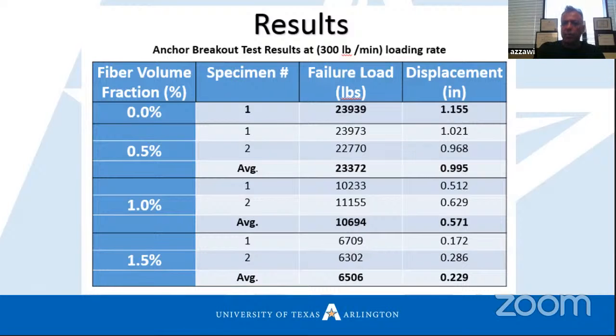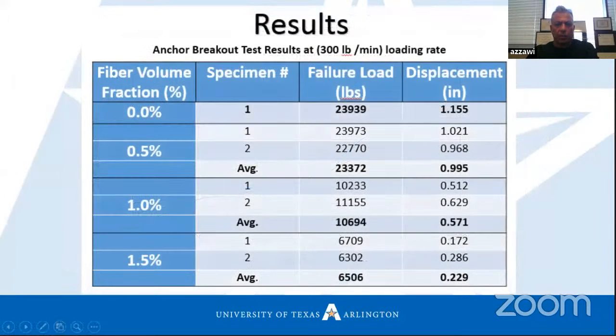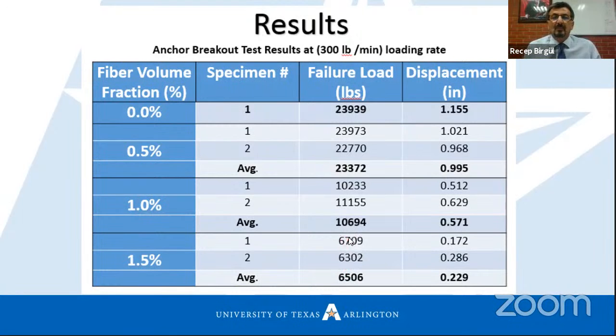So with synthetic fiber, I recommend going with 1% fiber dosage, not more than 1% fiber. I don't recommend going with more than 1% fiber with synthetic fiber. With the steel fiber, yes, we can go more than 1%, but with synthetic, increasing fiber more than 1% will really affect the workability and also the compressive strength. That's what we noticed from the test.